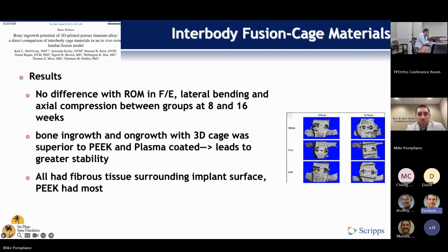In general, your PEEK can be less stiff, but that's not necessarily always the case depending on the structure of the metal. So then you get into not just the biomechanics, but the biology, right? And that can be modified now. You can do the acid etching, and the different surface treatment of a metal can markedly change the way it behaves, even though it maintains its hydrophilicity. It'll change the amount of cellular messaging and biologic behavior.